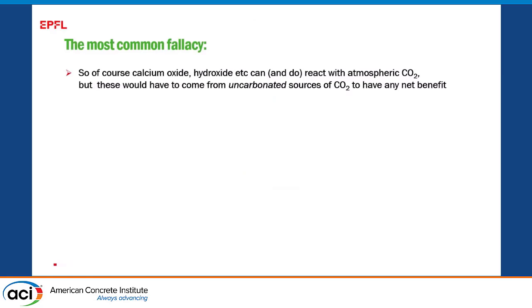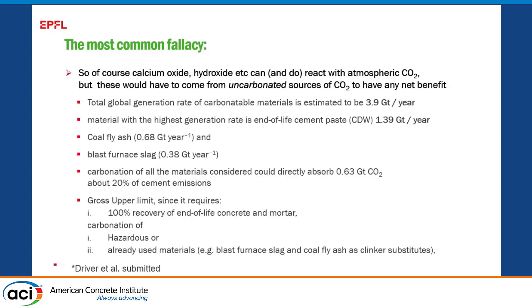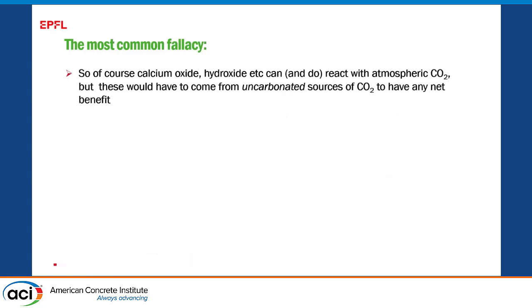So there are a lot of claims that we can add calcium oxide, calcium hydroxide to concrete. It will absorb more CO2. It's kind of true, but only if this calcium oxide or calcium hydroxide came from uncarbonated sources would it have any net benefit. And we've been studying this in detail for the past 2 or 3 years. And the problem is we've got very, very limited amounts of these materials. These are some of the figures here. I'm sorry I can't show you the much nicer figures, but because the paper's under review, I can't use those yet. But basically the end of story is this can contribute, it can be significant. We should recarbonate these materials, but it's going to be a very small amount.